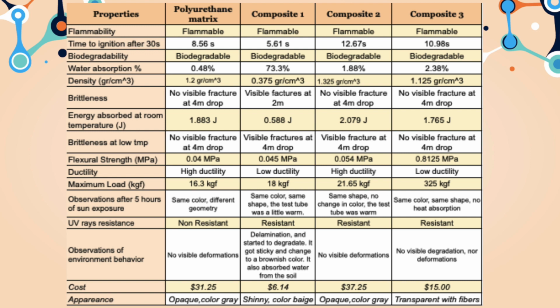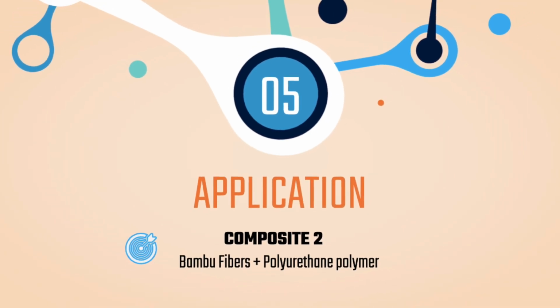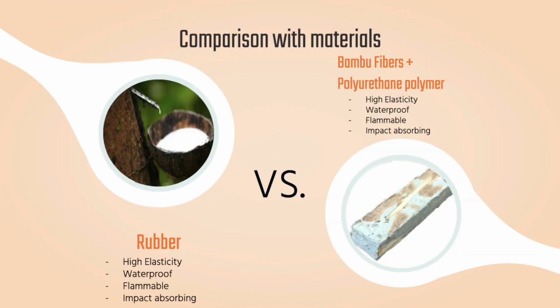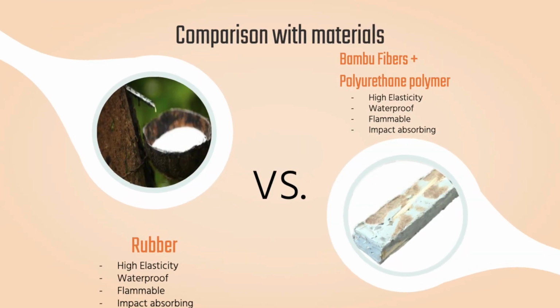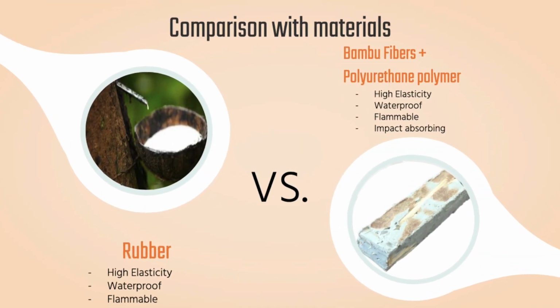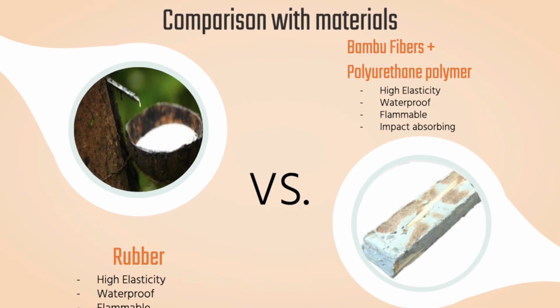We obtained this value with the bending test, knowing the maximum load applied at the moment of the fracture and the cross-sectional area of the test tube. The second composite presented high ductility and was the most resistant to UV rays. We determined this with the sun exposure test. The most similar material that we found to the bamboo polyurethane polymer is rubber, because they share many characteristics such as being waterproof, having impact absorbing properties, and being flammable.